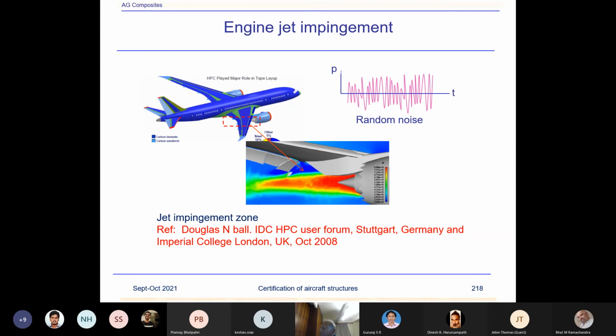The temperature would be less than 70 degrees centigrade, because our design condition for this is around 60 or 70 degrees centigrade maximum. So they are not in a very high temperature zone. All the high temperature zone is over here. So these parts don't lie in that zone.